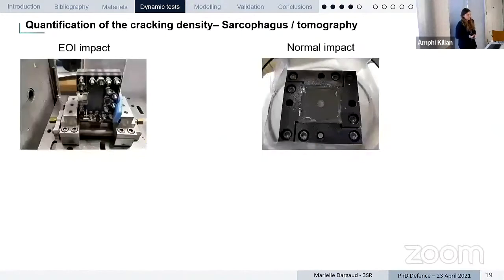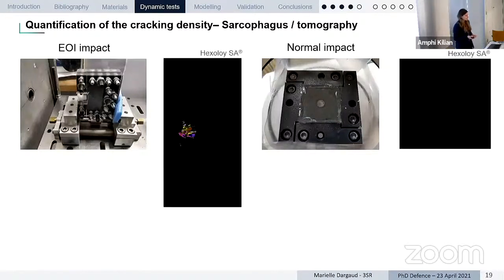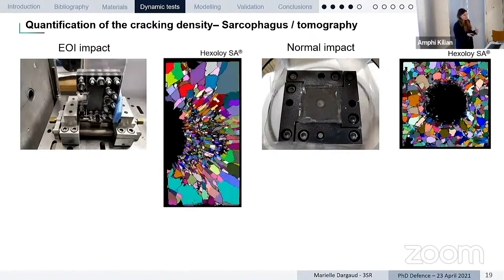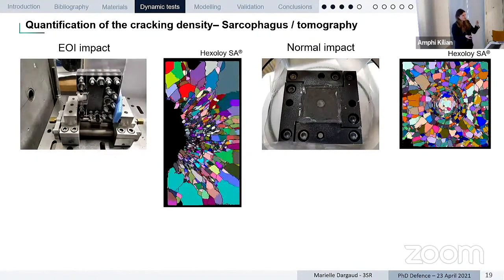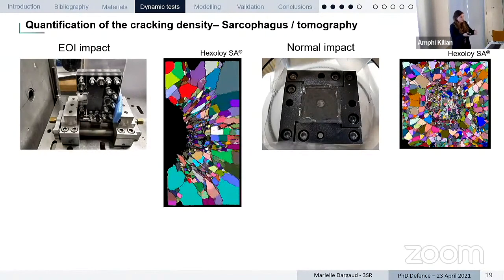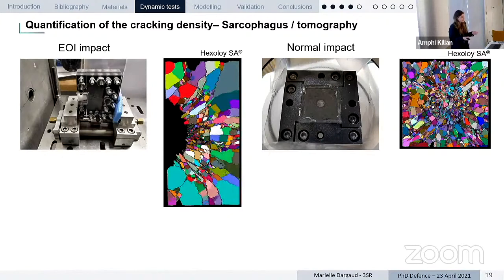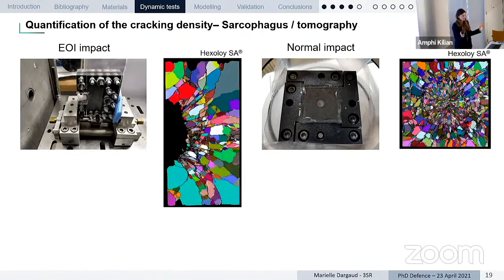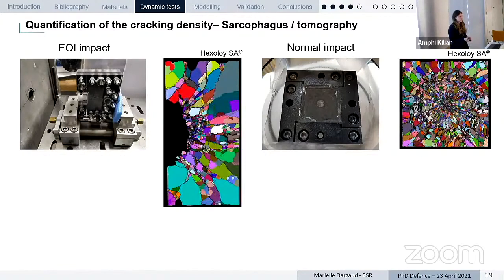Now, the idea is to quantify properly this cracking density. To be able to quantify it at a specific location in the tile, in the post-mortem sample, we had to keep all the fragments in position upon impact. For the edge-on impact test, we use a sarcophagus configuration with a transparent polycarbonate sarcophagus. And for the normal impact, we used a metallic sarcophagus, but after the impact, we infiltrated the fragments to keep all of them in one single piece.